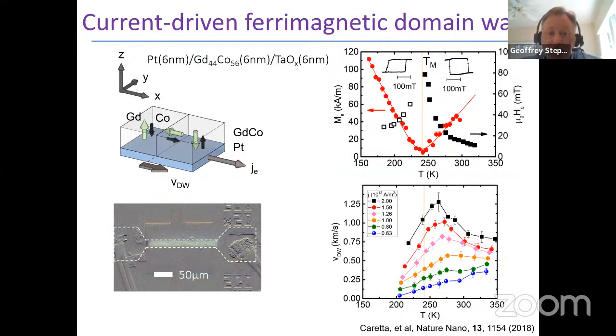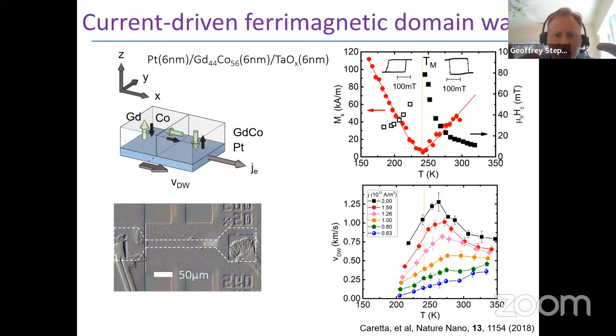So the sublattice moments have different temperature dependence. There is a temperature at which the sublattice moments balance one another, and that's the temperature at which the net magnetization is zero. And there's a different temperature at which the angular momentum balances on the sublattices. At the magnetic compensation temperature, there is finite angular momentum. At the angular momentum compensation temperature, there is finite magnetization.